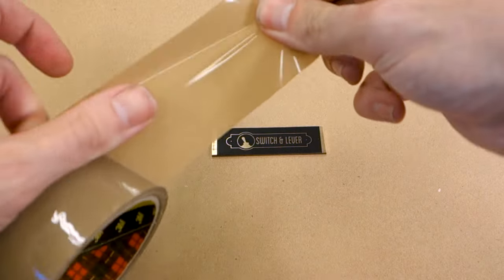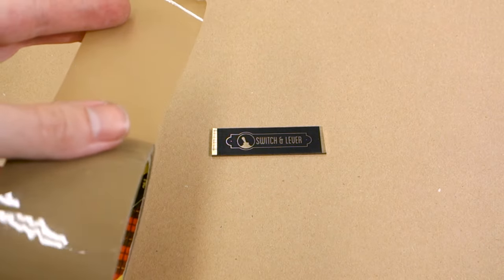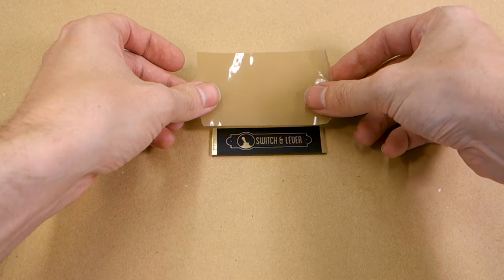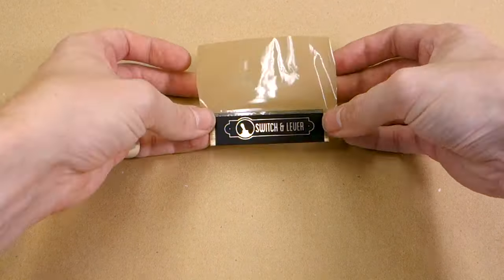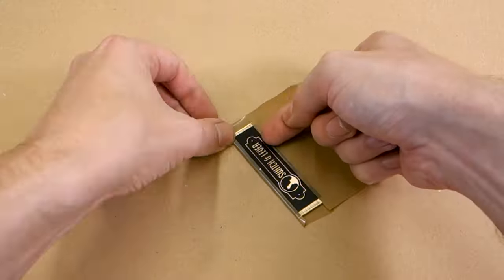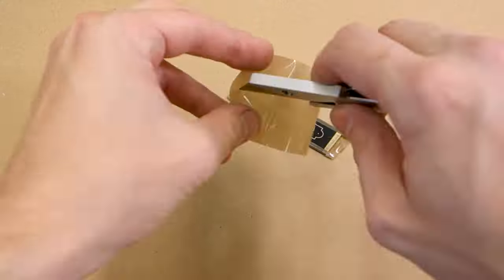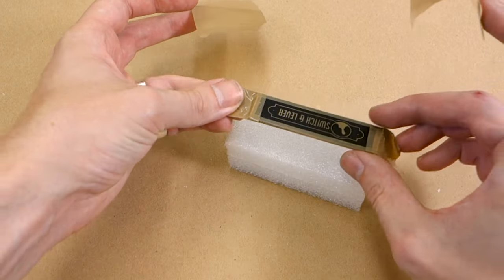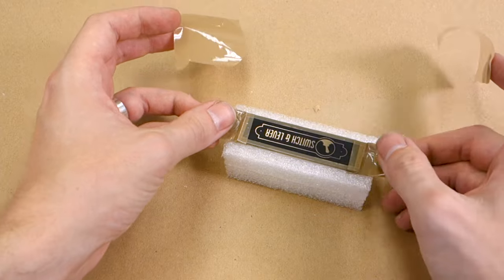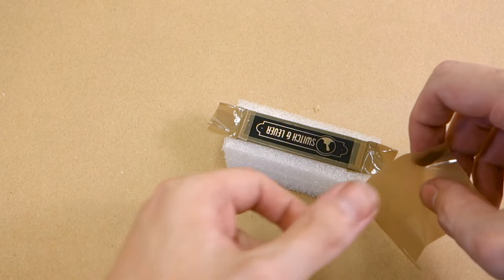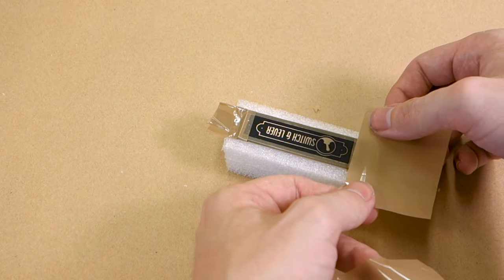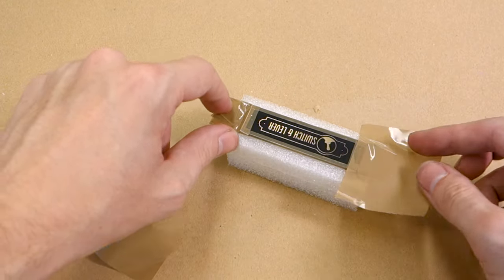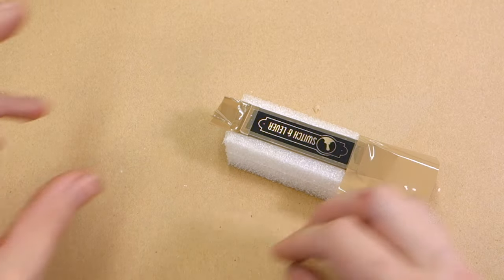The one thing left to do before we get to etching is to block out the rest of our plates with packaging tape to prevent any etchant going anywhere we do not want to etch. The only place you want exposed is the design you want to etch. As I want to float my plates in the etchant to help the removed material fall out rather than accumulate in the etched areas, I tape the plates onto a piece of closed cell foam which will help everything float slightly below the surface of the ferric chloride.